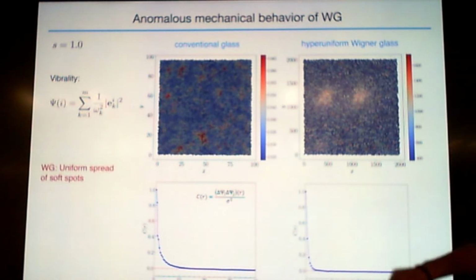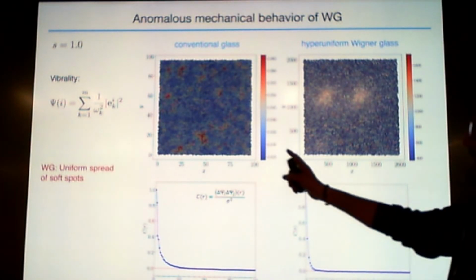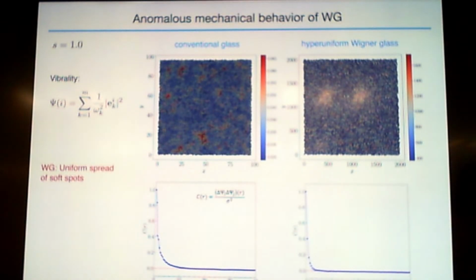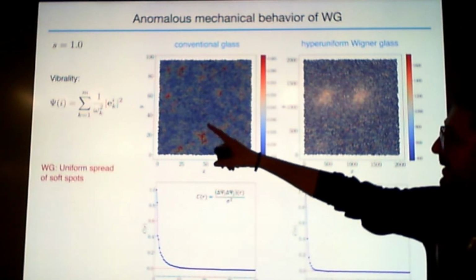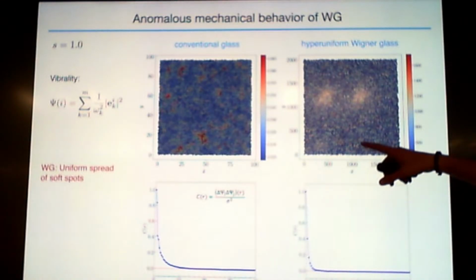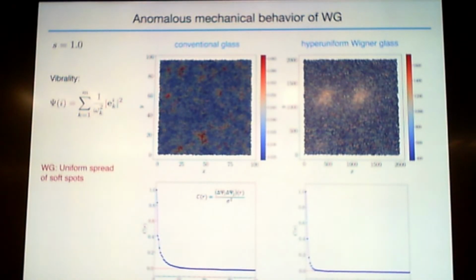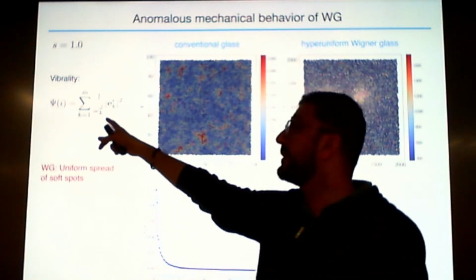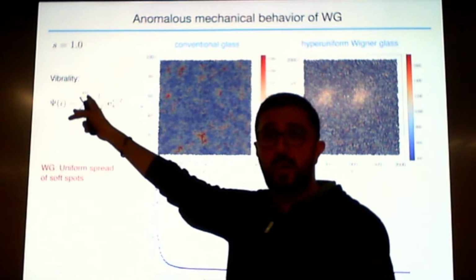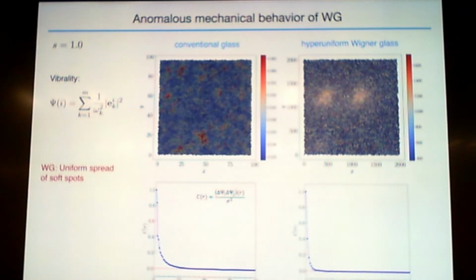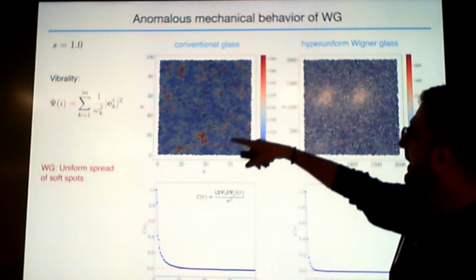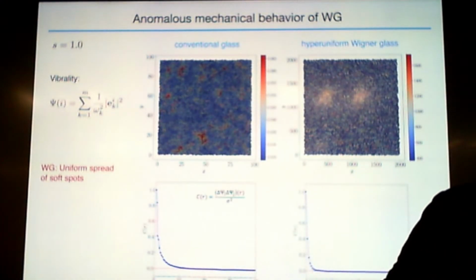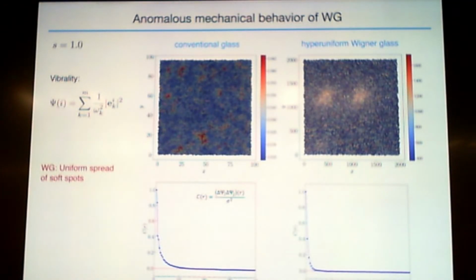Yes, thank you, Tom. All right, I'm now going to show you some mechanical differences between our glasses and, for instance, Lennard-Jones glasses, conventional glasses. You can measure the softness, the vibrality. What we do here is we write down the Hessian, the dynamical matrix, where the lambdas are the omegas squared, the eigenvalues, and the eigenvectors are the e's. If you sum up over all modes, you get the so-called vibrality, given here in the color bar. The higher vibralities are the so-called soft spots in glasses.